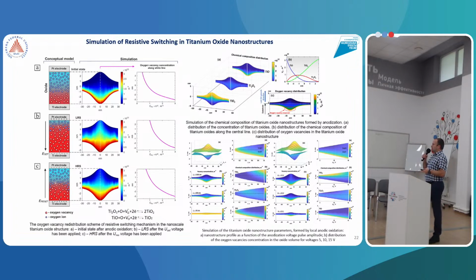state. On the right side we show modeling of the chemical composition of the titanium oxide nanostructure formed by the anodization process and the distribution of chemical composition in the depth of the nanostructure. We simulate the titanium oxide profiles as a function of anodization pulse voltages, and the distribution of oxygen vacancies concentration in the volume of these oxide nanostructures. We produce this simulation in the MATLAB program.